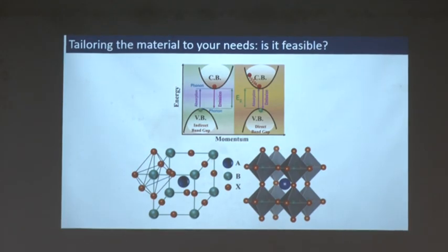Such information we can obtain from simple measurements, or when we are thinking about a material, we can perform quantum chemistry calculations, and we should see where the bottom of the conduction band and the top of the valence band are, and when one is above the other, it is okay. When it's not, we should choose.